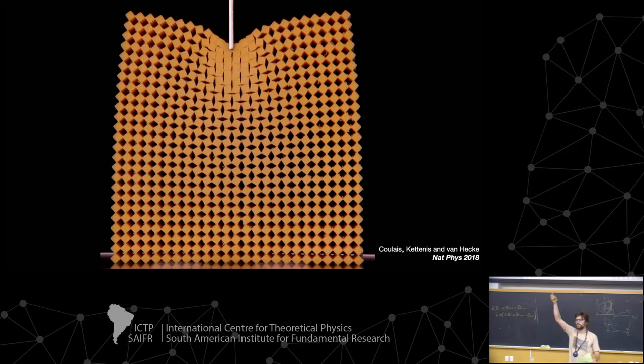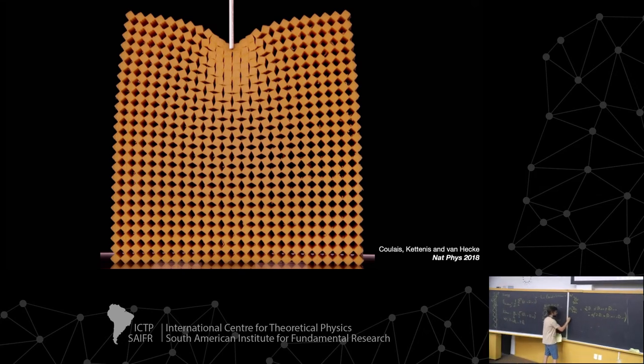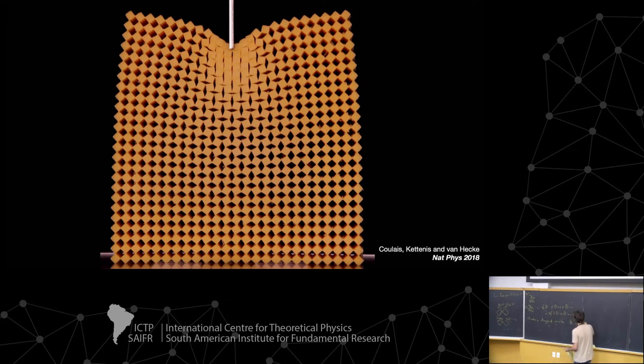What's interesting perhaps is to look at the continuum limit. We're interested in the typical decay length, so the decay of this anti-ferromagnetic order. So there we want to assume that things counter-rotate and look at how this counter-rotation decays in space. So here, what we do is we introduce a staggered variable phi, which is, I guess, what we started from. We take a different convention for the ones that are ranked odd and the ones that are ranked even. And so what we find if we do this is the equation we had before Xiaoming corrected me. Plus alpha. Plus this one's going to have a minus now.